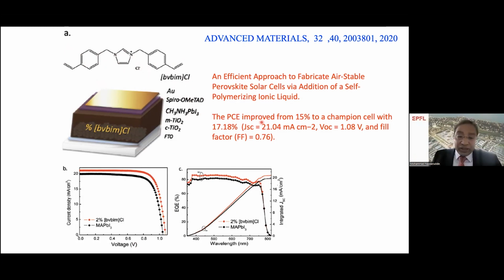So we are using only methylammonium iodide, which is a less stable compound. At that time, the efficiency was not high, 15%. By using this self-polymerizable ionic liquid, we increase the efficiency from 15% to 17%. The corresponding IV data and IPCE data are shown here.